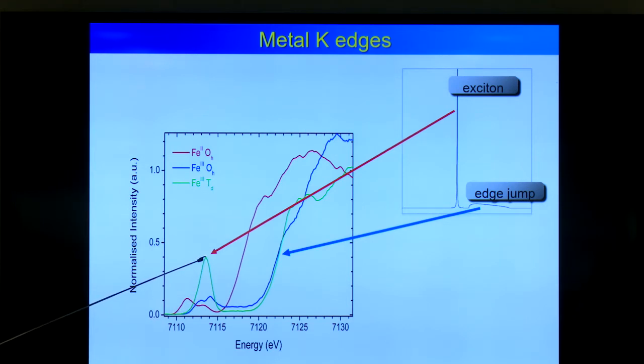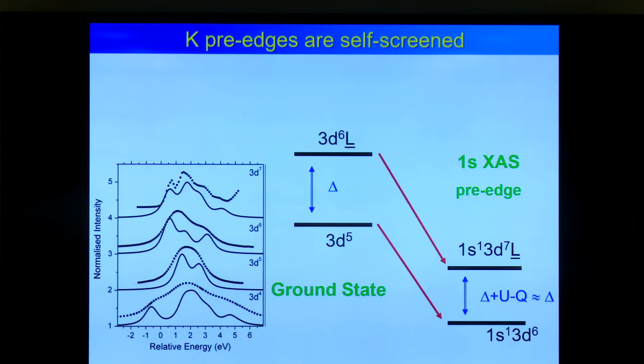And the intensity is now mainly given by the symmetry. So the tetrahedral is because the broken inversion symmetry is much higher than the octahedral with inversion symmetry. So if you want to do quantitative calculations on this spectrum, then we face some new problems, different from soft X-rays. So the pre-edge itself is easy because it's the same as L-edge. You do a multiplet calculation on your pre-edge, so I just do d4, d5, d6, d7. And then you compare your multiplet calculation with your pre-edge spectrum.